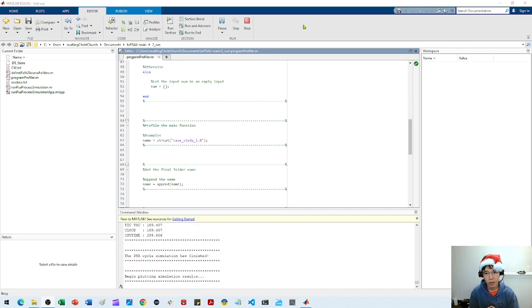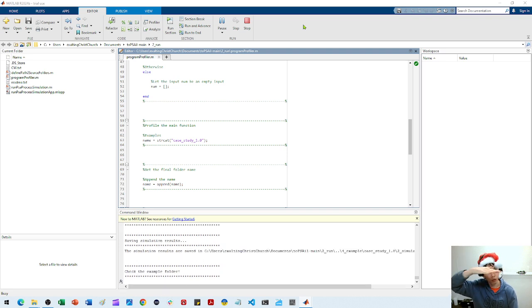So basically, the Skarstrom PSA cycle consists of four distinct steps, right? First, it's repressurization to the high pressure using the raffinate product, in this case, pure oxygen. Once you reach the high pressure, you can feed into the bottom end of the adsorption column so that the feed, which contains nitrogen and oxygen, can be separated. Then you run the high pressure feed until breakthrough happens, which means you start to have some nitrogen coming out from the top, and you don't want that, so you need to stop. Again, because adsorption capacity for these adsorbents with finite mass is limited.